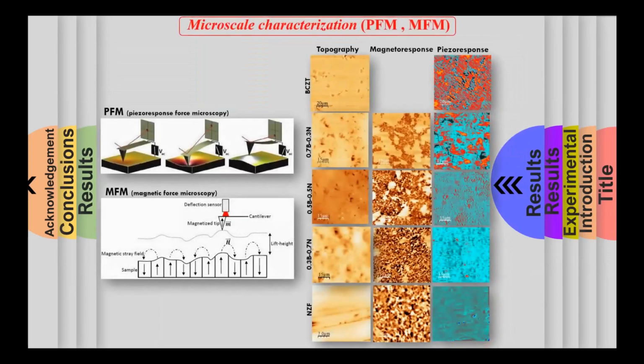To identify the local ferroelectric and magnetic behavior, the composites were studied using scanning probe microscopy techniques such as piezo response force microscopy, PFM, and magnetic force microscopy, MFM. Here the probing tool is basically a cantilever with a tip radius of around 20 to 30 nanometer. In PFM, the cantilever scans the surface in contact mode and monitors the local piezoelectric surface deformation, while MFM uses